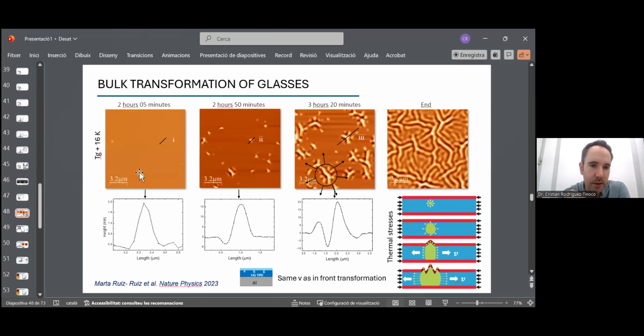Okay, and this is what we get. Very interesting. So initially we have a completely flat surface, but eventually we observe the emergence of some bumps. Okay, when time goes on, we see more and more bumps which then start to grow laterally until all the sample is completely filled with this kind of structures. Okay, so completely corrugated. Okay, the interpretation we make, which is compatible with what we said with calorimetry, is this. We start forming these regions which have become a liquid, which then grow. When they grow, they reach this capping layer, and remember that the liquid has higher density than the glass, so it pushes this capping layer, and this is what we see here, okay?